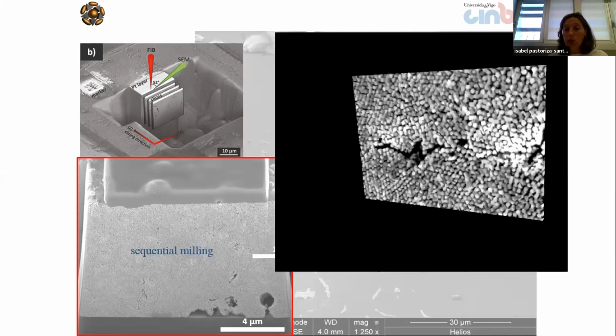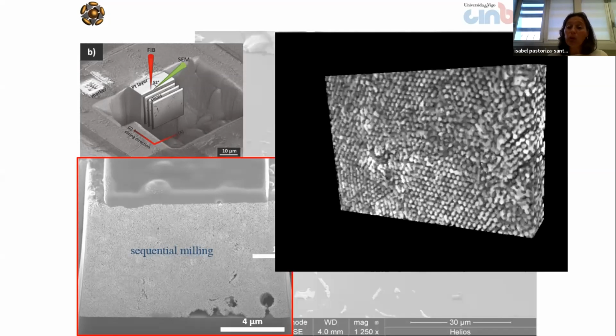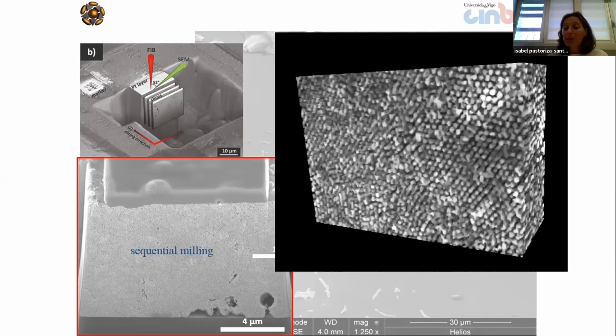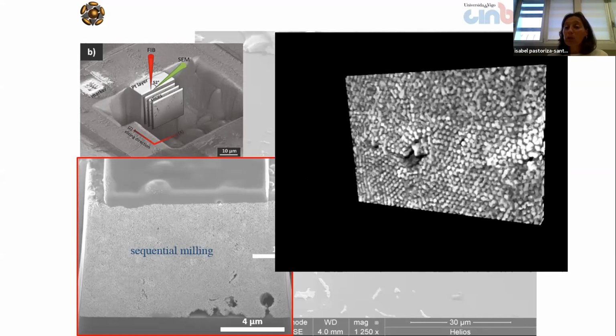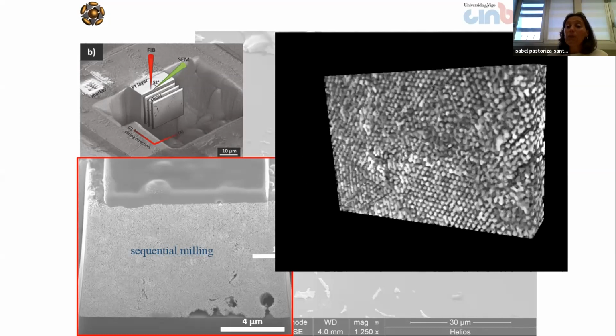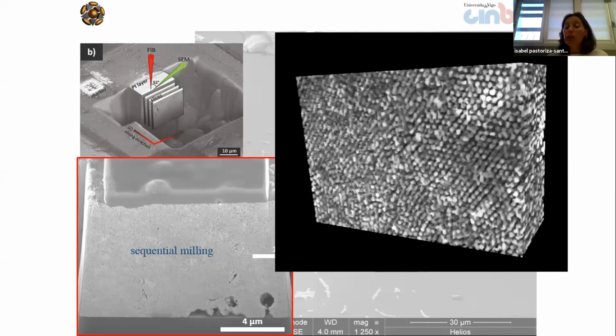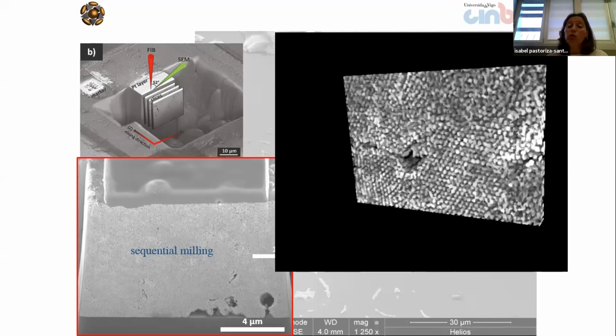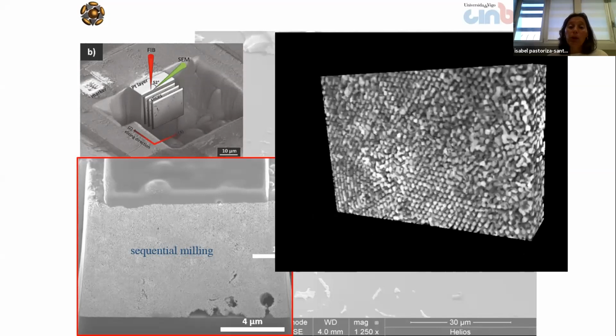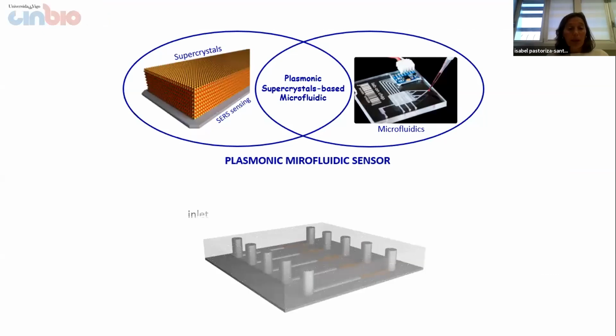This is the result of the 3D reconstruction, where we can see that in the inner part of the structure the particles are well ordered and close packed. So the nice thing is that we have integrated supercrystals into microfluidics, and therefore in this case we have a